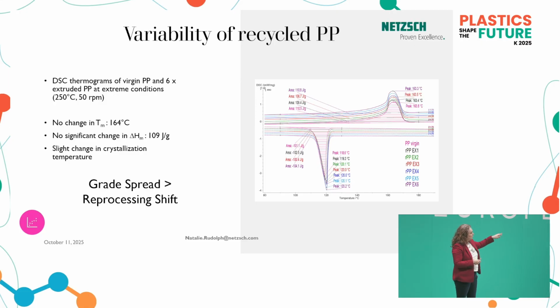The different DSC curves show material that was 6 times extruded compared to the virgin, and the thermal fingerprint doesn't change. So a learning was definitely that the spread between grades is much more important than the spread we get through reprocessing.